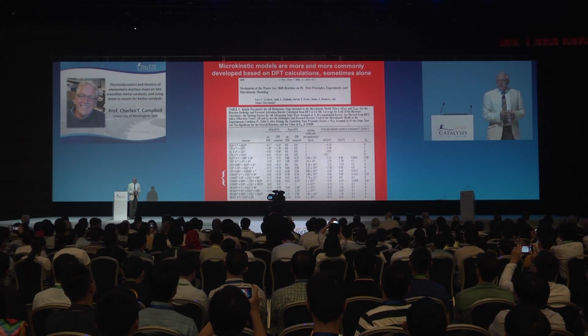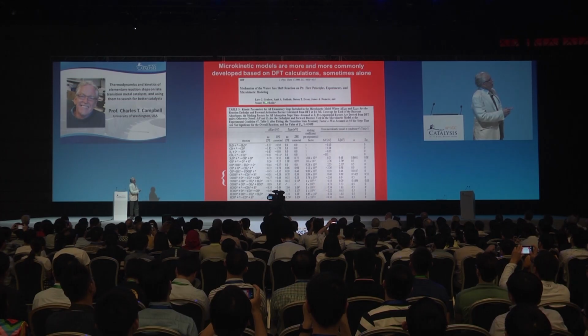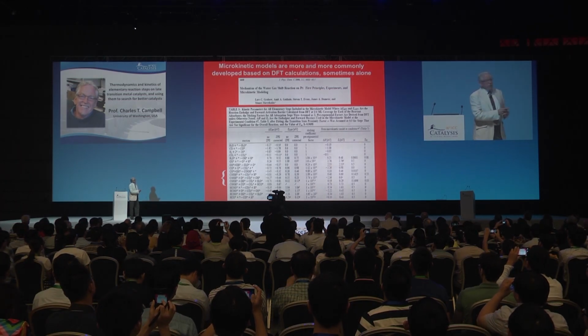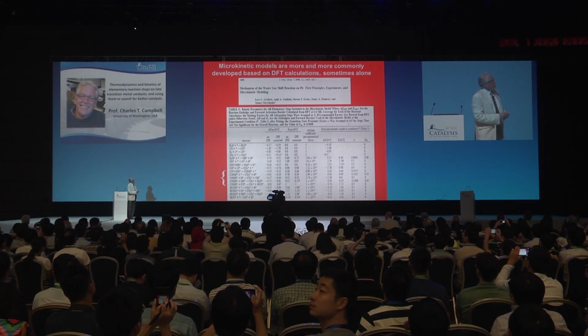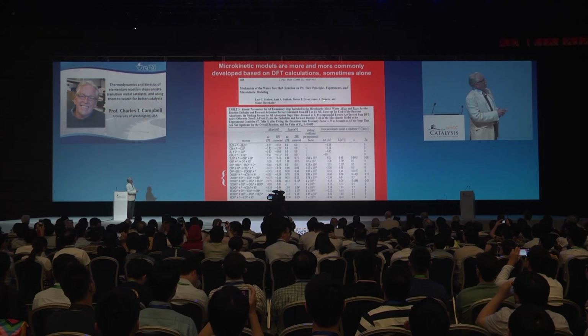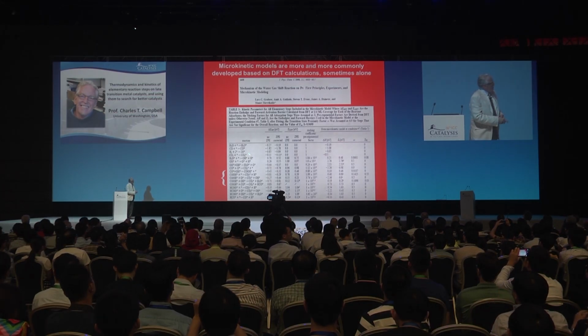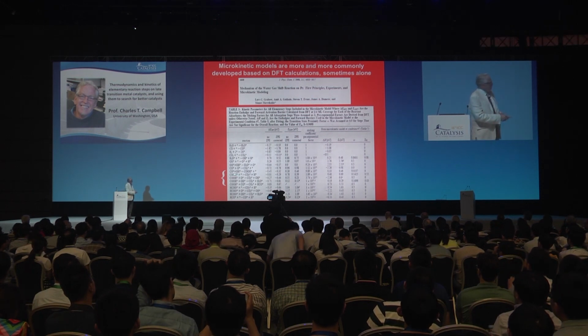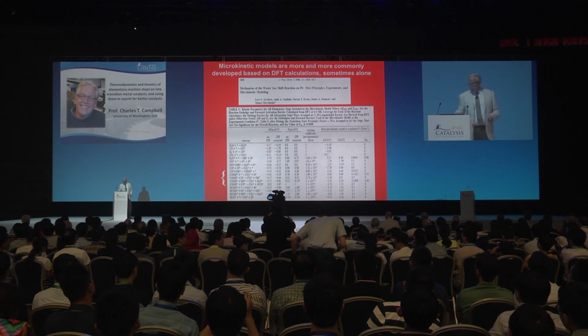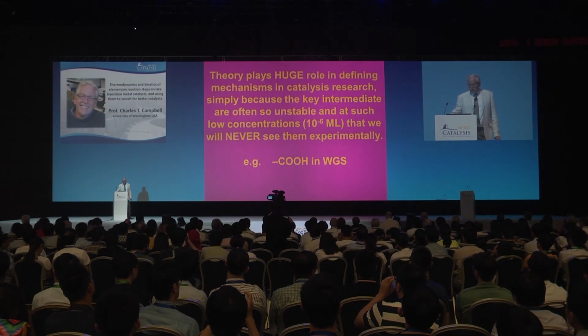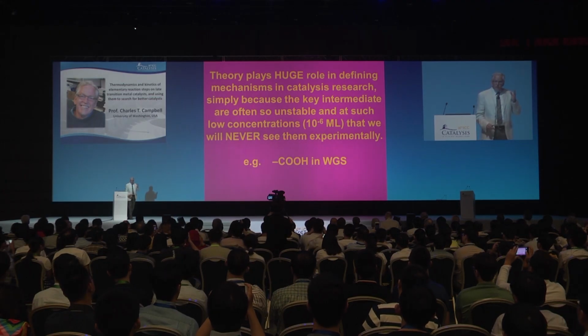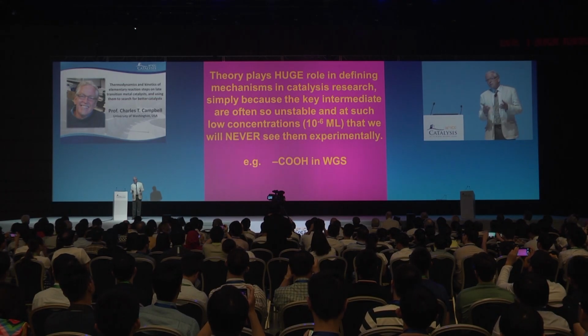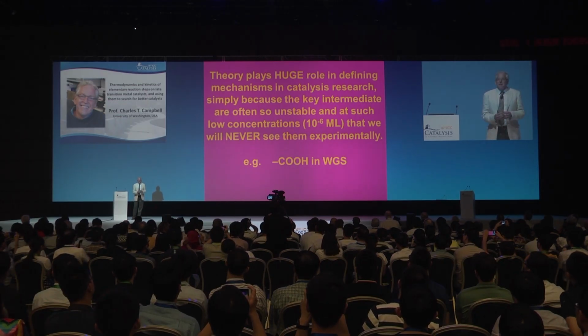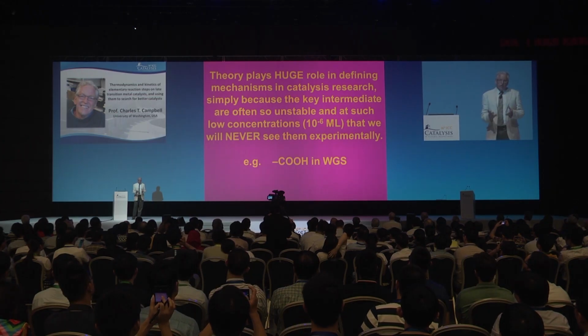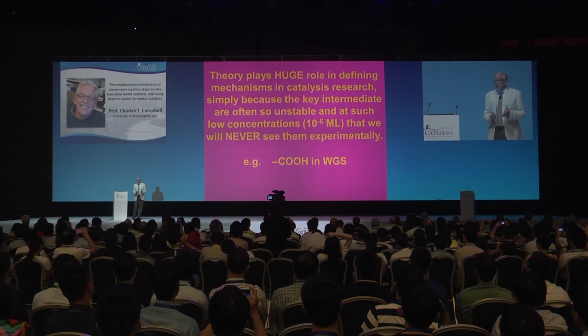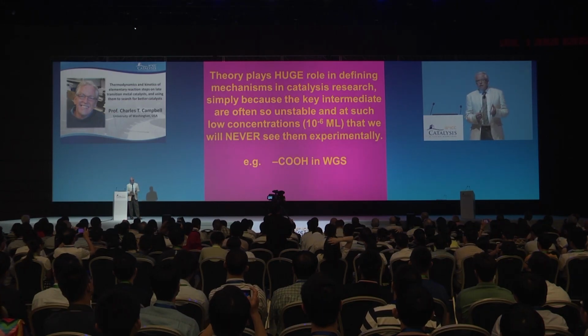It's much more common nowadays to see microkinetic models that are based on density functional theories, and here's an example from Manos Mavrikakis and Lars Grabow, who's in the audience somewhere, and Jim Dumesic, where they used density functional theory to study the same water-gas shift reaction, but on platinum 111. And these are the elementary steps. And this was an important paper because it first talked about this carboxylate intermediate that's crucial in that reaction, which reminds me to point out, I show the errors, and I've sort of become famous for pointing out the errors in density functional theory, but I also am a strong proponent of density functional theory, and it really has helped us tremendously in the science of catalysis.